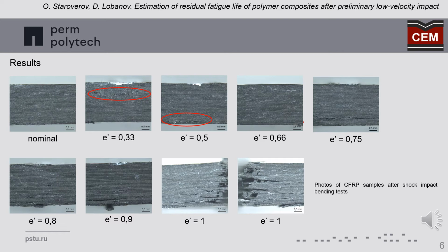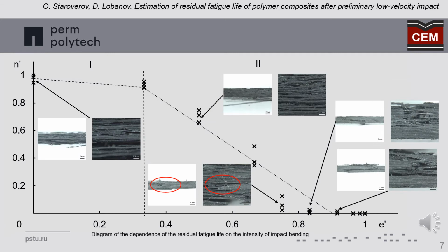The photo of fractures of specimen E1, tested for fracture in three-point bending by impact with the falling weight, shows multiple fiber breaks and delamination in the longitudinal direction, in relation to the orientation of the reinforcement layers. As a result, experimental dependencies of the influence of different intensity of impact bending on residual fatigue life of carbon fiber specimens were obtained.